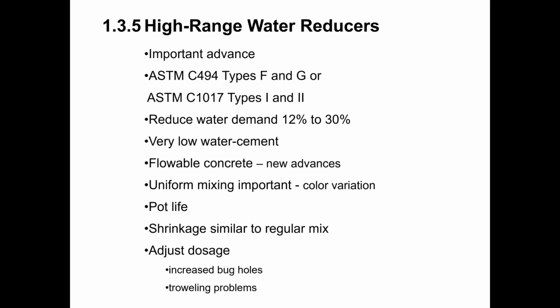Now, early generations of high-range water reducers had a fairly short pot life. And so what that meant is that you could start pouring a truck of concrete, and maybe it had an 8-inch slump when you started pouring, but then very quickly it lost slump and went back to that natural 4-inch slump. So definitely that could complicate the casting process.